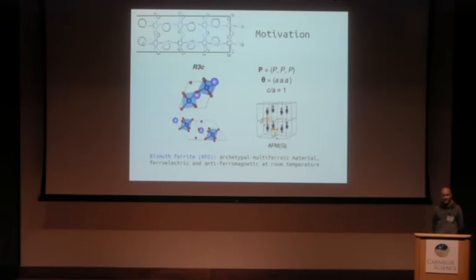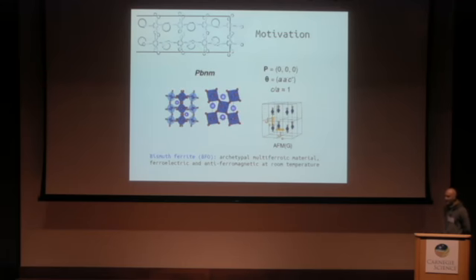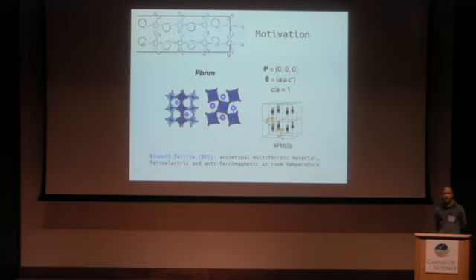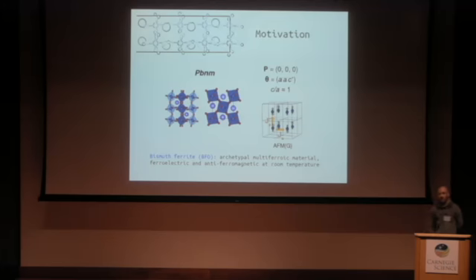The magnetic order in this case is antiferromagnetic G-type order, which means the atomic magnetic moments are oriented anti-parallel in any direction, both in-plane or out-of-plane. In bismuth ferrite there is a competition between this ferroelectric magnetic phase and an orthorhombic non-polar phase, PBNM. When you heat it up at ambient pressure conditions, at some point it becomes paraelectric and adopts this phase. Or if you compress it under pressure, it also stabilizes in this non-polar phase. The magnetic order in this case is also G-type antiferromagnetic, the same as in the ground state, with a different pattern of oxygen-octahedral rotations.